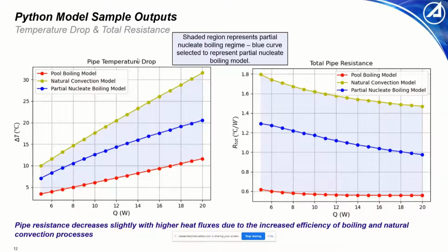So you can see nucleate pool boiling is our most efficient form of heat transfer, resulting in the lowest total resistances and the lowest temperature drop. After that is partial nucleate boiling. The term partial nucleate boiling can really refer to a process that corresponds between these red and these green curves. There isn't typically a discrete model for partial nucleate boiling.